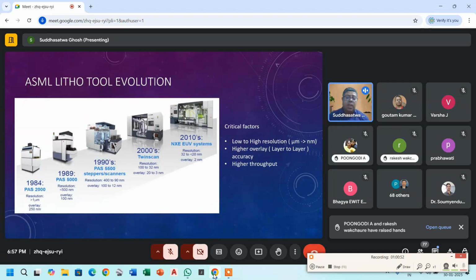And as you can see, as we have gone for finer and finer resolution, the overlay accuracy also has to be much higher. For example, when we are talking about resolutions of 32 nanometers, the overlay has to be accurate to less than approximately 3 nanometers. When we talk about less than 20 nanometers of lateral resolution, the layer to layer accuracy has to be less than approximately 2 nanometers. And last but not least, all of these machines are driven by high throughput, which means a higher number of wafers per hour.